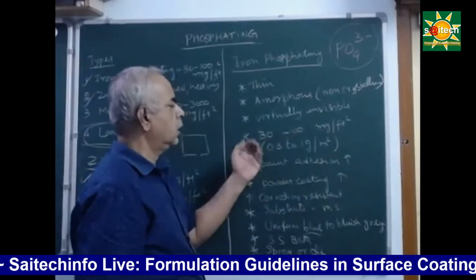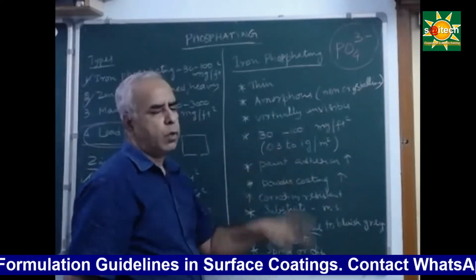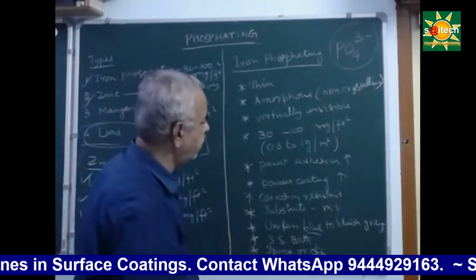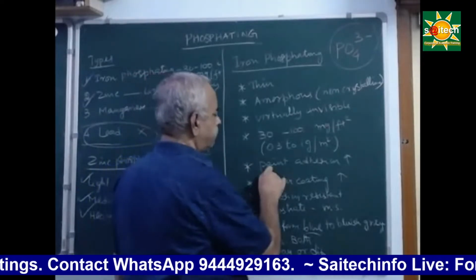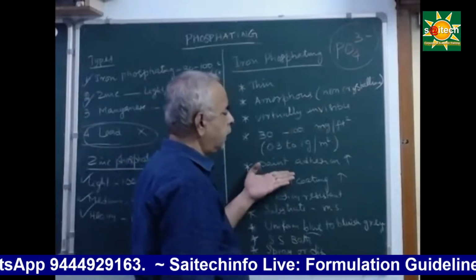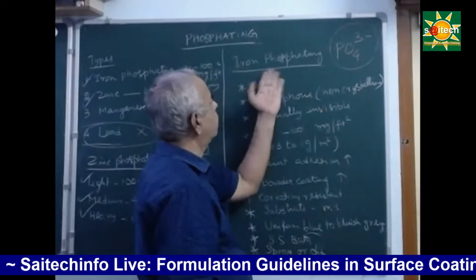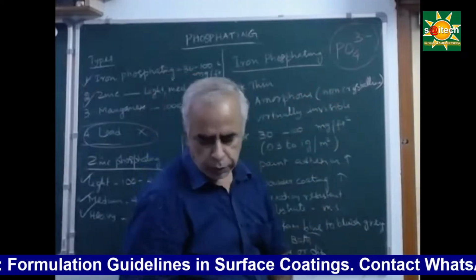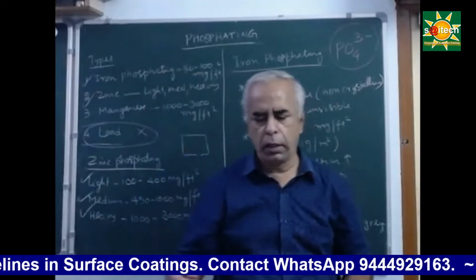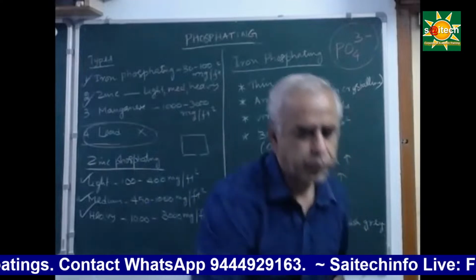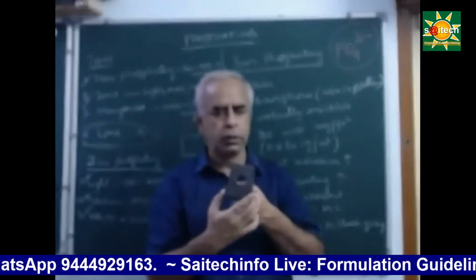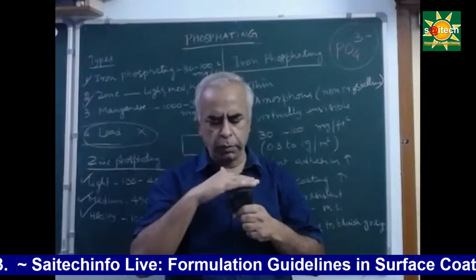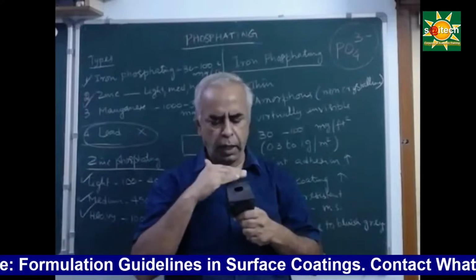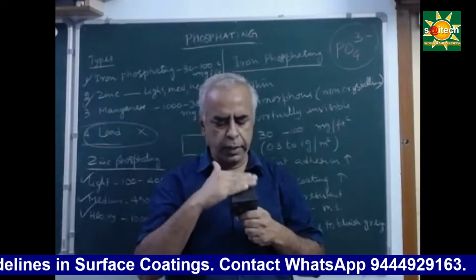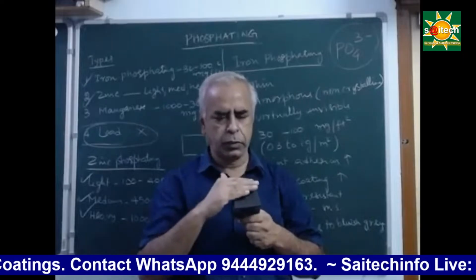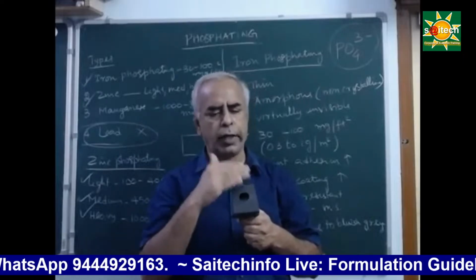So normally the coating weight is 0.3 to 1 gram per square meter. Then paint adhesion is improved with the help of this iron phosphate coating. So what you do is, if you have any component, and let me consider this component. So we have the component here. First you have to clean it properly, ensuring an oil free, dust free, rust free surface. Then you can give a coating of iron phosphating.